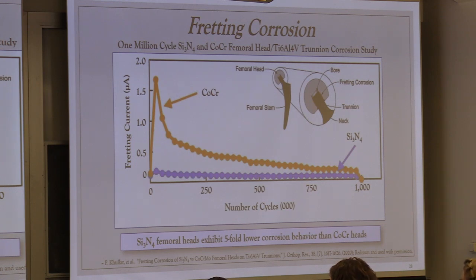Ceramics, in particular silicon nitride, have 1/5 the overall corrosion characteristics of these metal-on-metal couples. So that's another reason. Now I searched for data to do comparisons on ZTA versus silicon nitride, but right now there is no data out there that I've been able to find that would suggest how silicon nitride compares to ZTA. I would suspect they're probably pretty close to being the same.